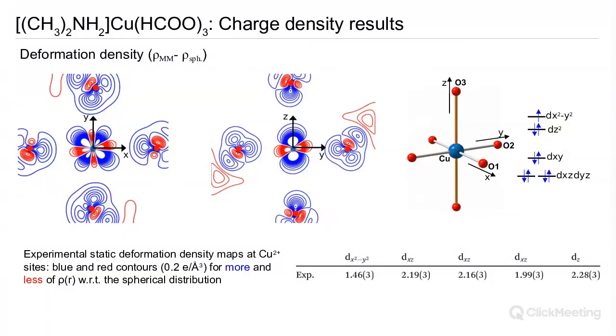We can take a look at the transition metal, the copper, and what I've plotted here are deformation density maps. So this is, if you like, the result of the multipolar model with the spherical distribution subtracted away, such that the blue corresponds to additional charge density in the system with respect to the spherical model, and the red corresponds to a deficiency of charge with respect to the spherical model.